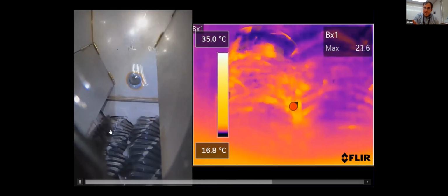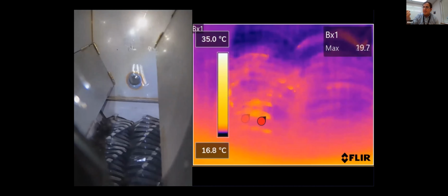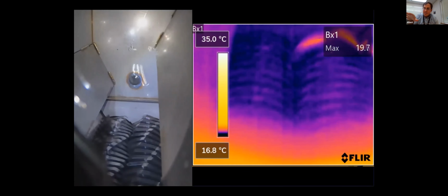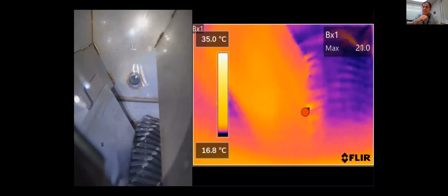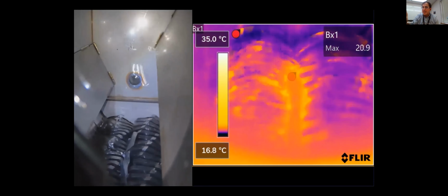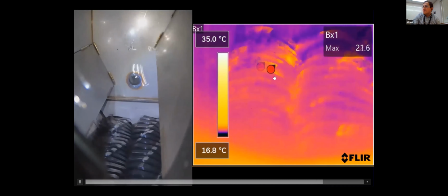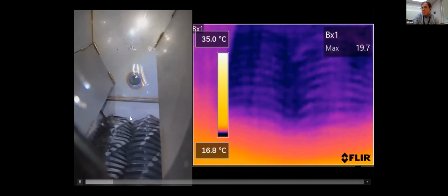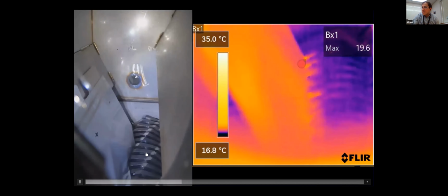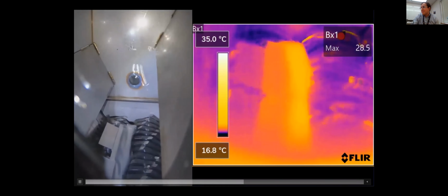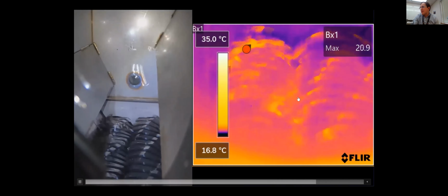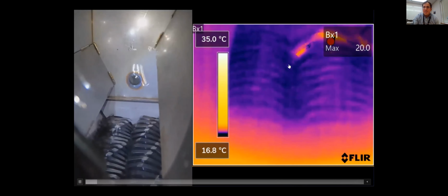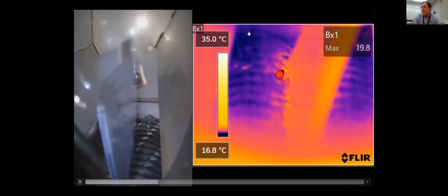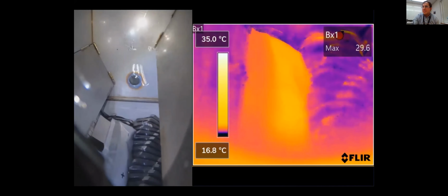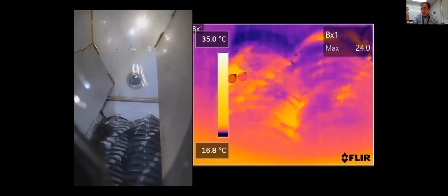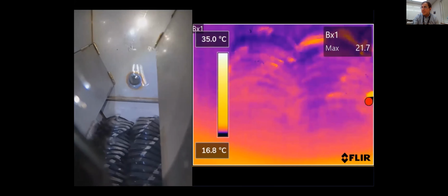So first, we discharge them. The second thing is the shredder is inerted with nitrogen, so there's no oxygen. So you don't have to worry about the electrolyte catching on fire just because of a spark being generated during the shredding. We basically have carefully designed everything so that that can be the case. You can see that the battery doesn't even heat up very much. We get up to maybe 34, 35 degrees Celsius, which is roughly 80 or 90 degrees Fahrenheit, barely warm to the touch. If you do this same thing with a charged battery, you will get an explosion.